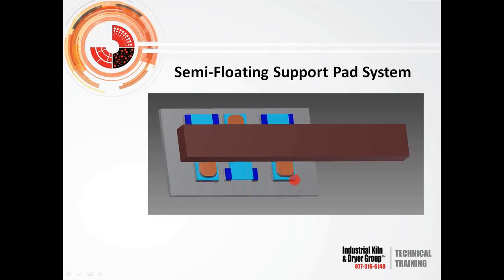That's a good point, because when we're talking about letting these things go long enough that you really create a high clearance, then if you have a system like this, they become even more vulnerable because of all the shell flexing. Right. Because once again, when it's at the bottom of the shell, it's seeing all the load. When it gets to the top of the shell, there's no load on the pads at all, and it just pushes them in, and then they bounce back out, and that's obviously what we call fatigue.